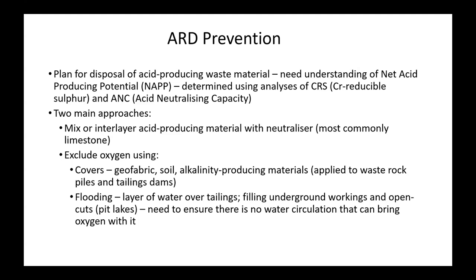So waste rock these days is often mixed or interlayered with neutralising material, which is typically limestone. And that has been very effective at quite a number of mine sites. And sometimes it's mixed in lifts, and the lifts are separated by clay to reduce the amount of percolation of the water through the waste rock piles. And then there are ways of excluding oxygen. So oxygen is required for pyrite to oxidise. So if you can keep it out, then hopefully you'll stop the whole process beginning.